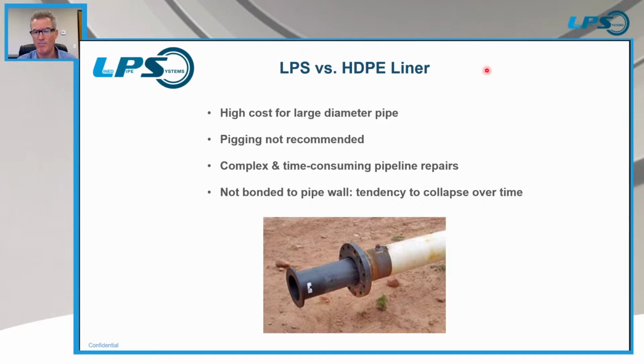They're also just not bonded to the pipe wall. So in most of the situations we know, it's not a question of if they'll collapse, it's when, and generally in that 15, 20, 25 year time frame, they will relax off the pipe wall. It'll be an issue. So it's not yet proven to be a really, really long-term solution.